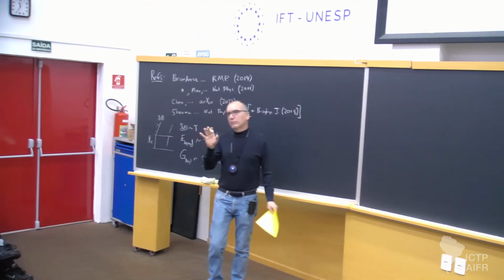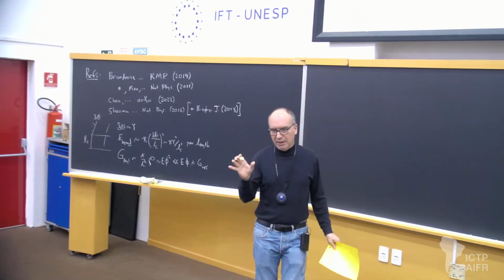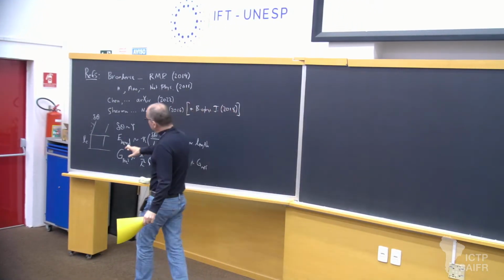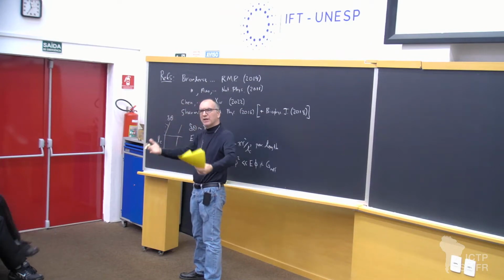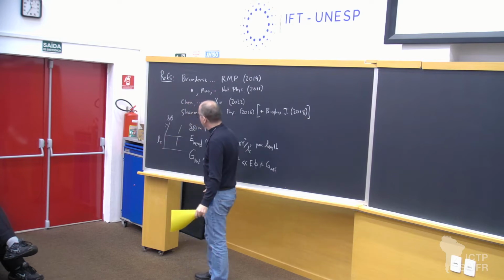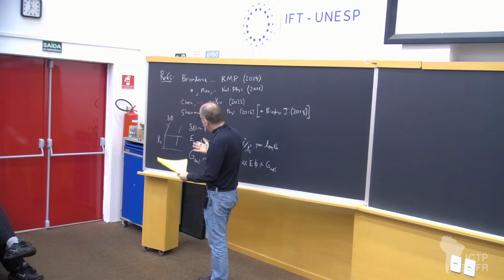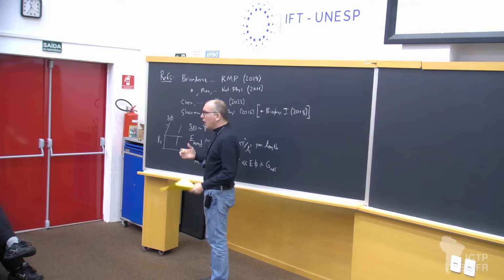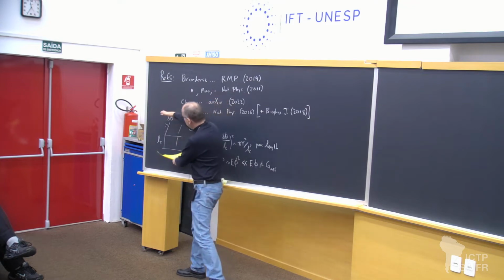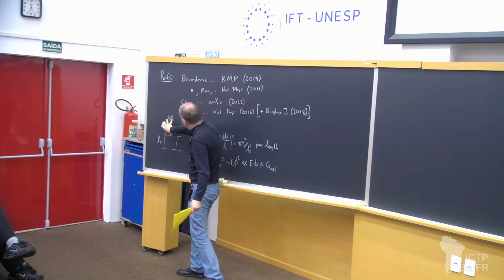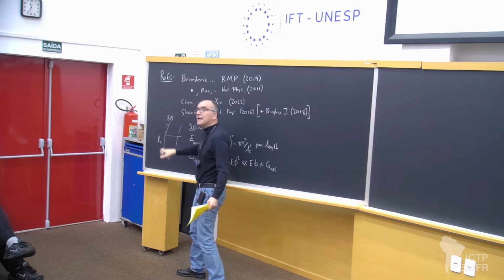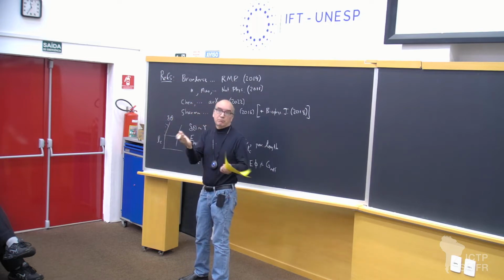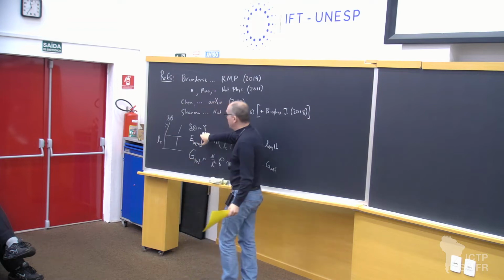We're going to look at a linear response regime, so this will be appropriate for linear elasticity. And the basic idea here, I'm going to sketch this in terms of a lattice. It works off lattice if you put in average values for things like separation between crosslinks. But thinking of that as a lattice spacing, a non-uniform strain might look something like this. So let's say this structure is going to be sheared this way, and if this pair of segments doesn't quite deform the way these do, there'll be some relative angle between the two, call that delta theta. That should be proportional to the strain that I impose to linear order. So quite naturally, that should be proportional to strain.